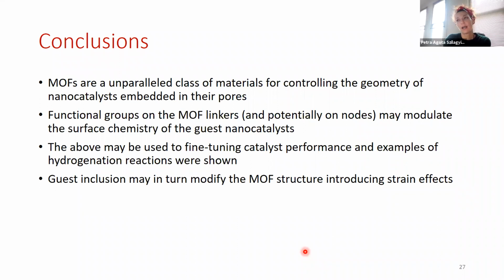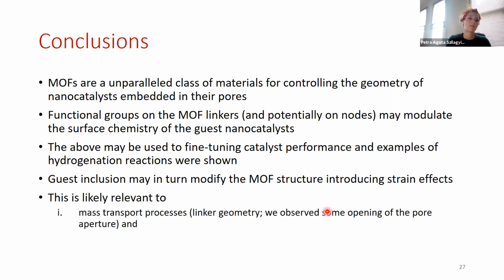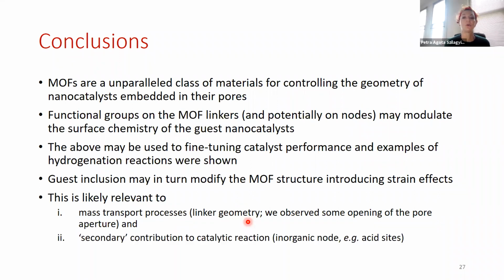The guest inclusion, so this is mostly to show how the framework fine-tunes the catalyst itself, but in return, the catalyst guest may also modify the framework, and it can introduce strain effects. And this may have relevance to mass transport processes. So in the example I showed you where the rotation of the linkers was blocked, we also observed that this was accompanied by an opening of the pore gates. And also we saw that there is some kind of a secondary contribution, for example, through the suppression of acid character of the inorganic nodes.